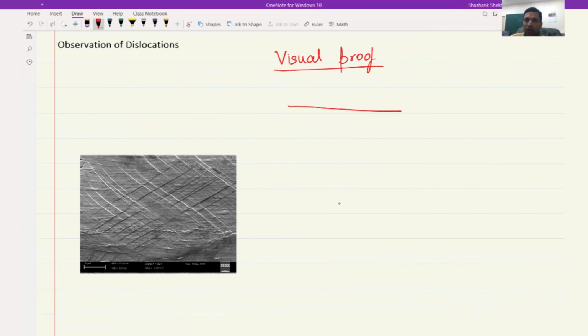You take a polished surface and therefore the atoms inside it are very well arranged, and when you look from the top, it will look like a very smooth surface. But now let's deform it a little bit. For example, you may compress the surface, and there may be certain slip planes, and dislocations, which we will introduce later, move in steps, causing step rises. One step would be equal to the distance of atoms, so it will rise like this, and when you have tens of thousands of these, it will become observable to the naked eye, and what you would see is something like a step.